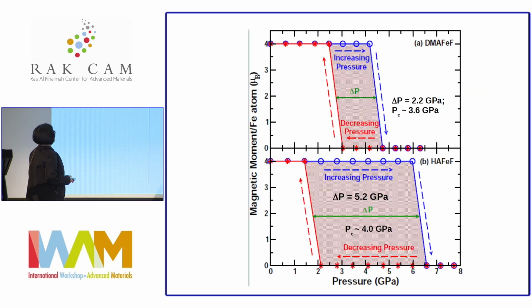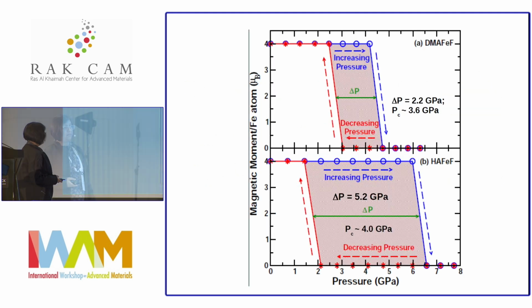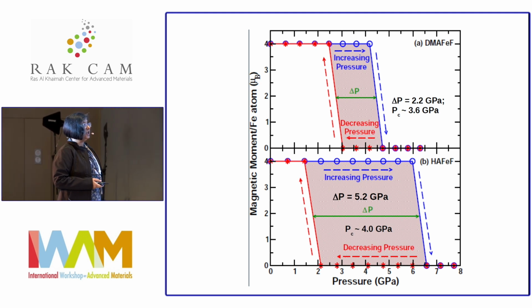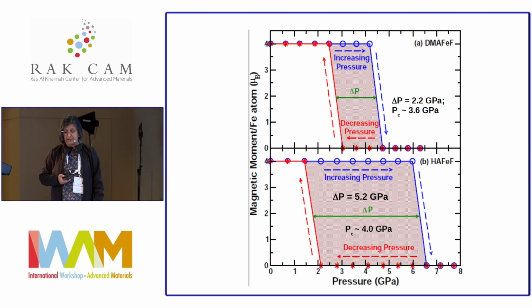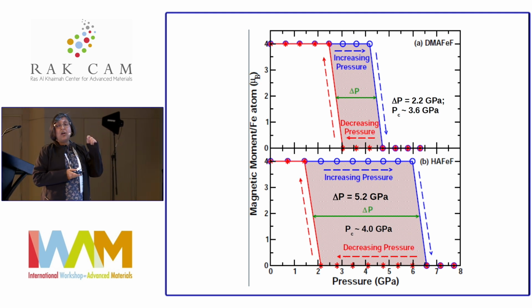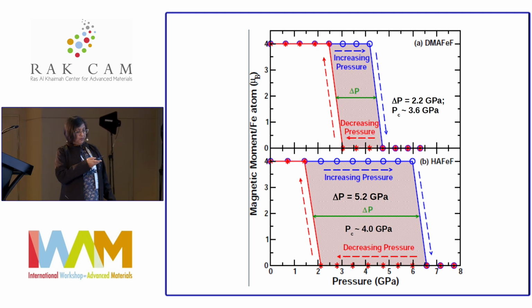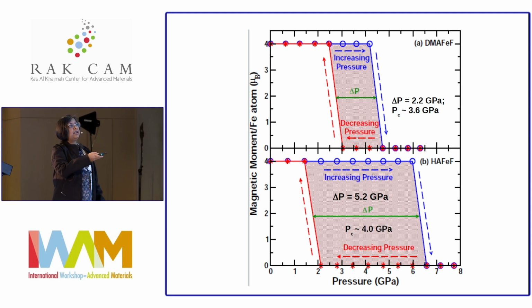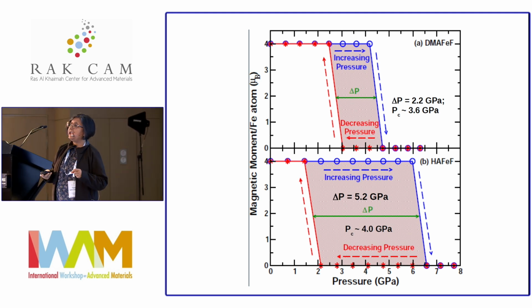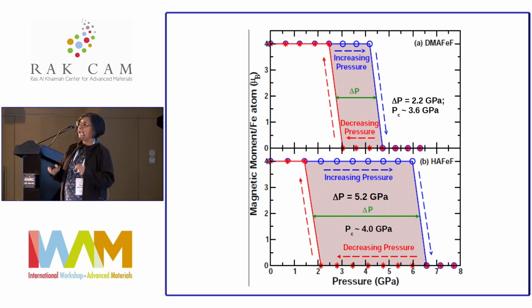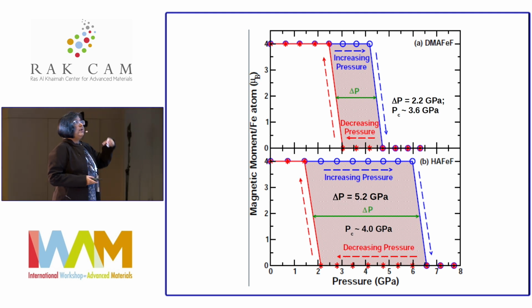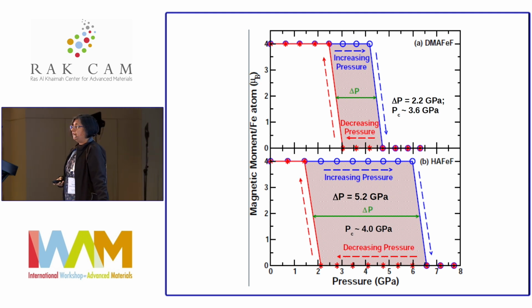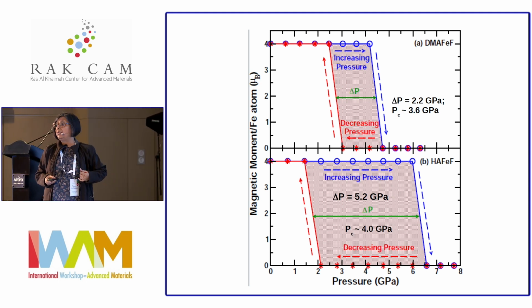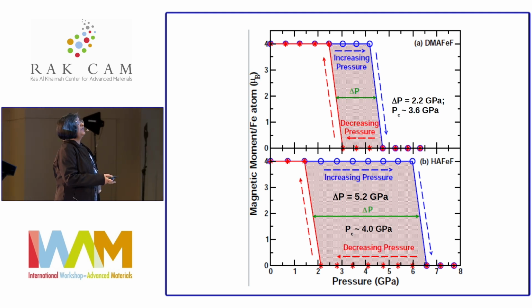So what we basically found is that by applying pressure, we do have a transition from a low spin to the high spin, with a critical pressure of about 3 to 4 gigapascal. And you can not only change the critical pressure, but most importantly the width of the hysteresis is tunable, depending on which kind of A cation you are putting in the middle. I didn't have time to get into all the details, but we found it is primarily driven by the elastic interaction.